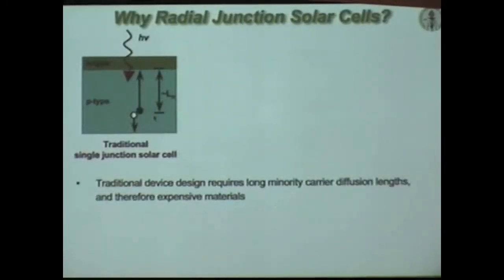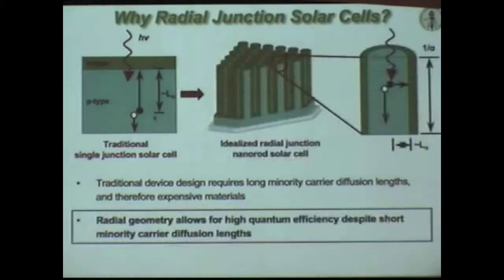The key experiment here is to vary the wavelength of light. For a planar cell, as I've said, very short wavelengths are going to be absorbed strongly, and they'll be within that micron active layer and give us high current yield. But very long wavelengths of light near the band gap are going to penetrate too deeply, and the current should die. On the other hand, same material grown exactly the same way at the same time, but in the highly packed nanorod structure should have the ability to collect carriers sideways for both the short and the long wavelengths. So that's a definitive check of whether or not we're on the right track.